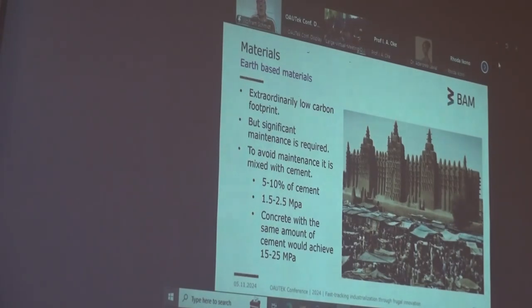But if you think about big cities, that would never work with the maintenance, and that is the problem, that people, in order to avoid the maintenance of these structures, put cement into the soil. And here they typically use something like 5 to 10% of the dry mass of the materials. The expected compressive strength would be something like 1.5 to 2.5 megapascals, which is very, very low. So we use a very high amount of cement for a very, very low strength here, which means we completely underuse such a high carbon emission material as cement.